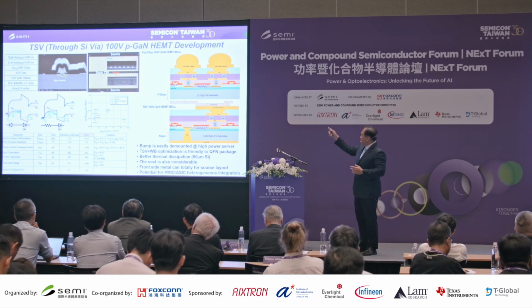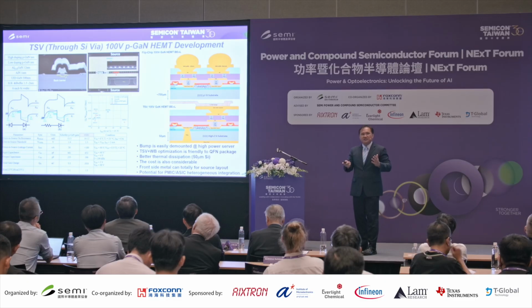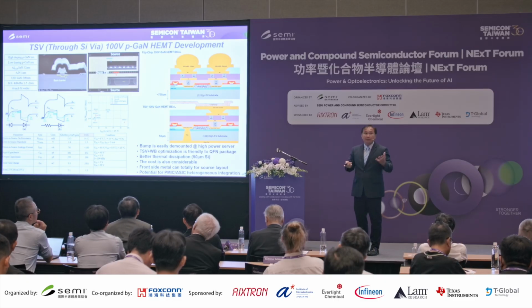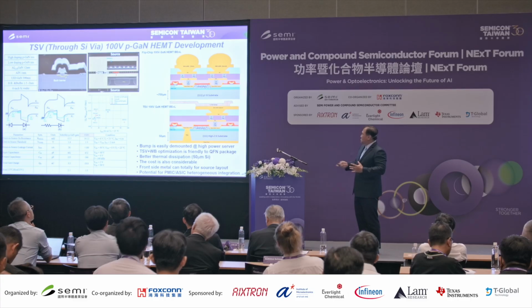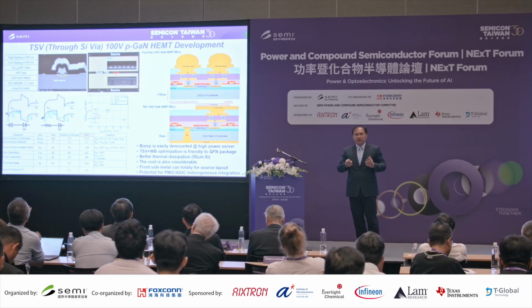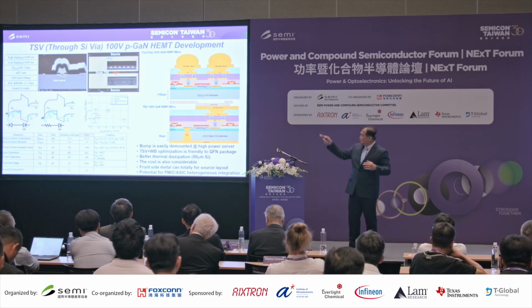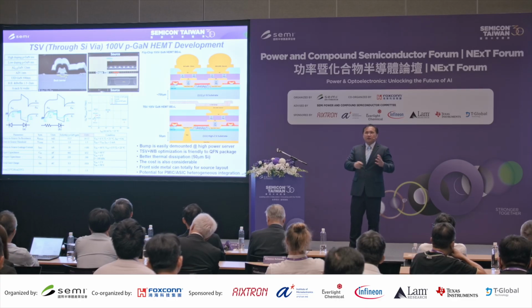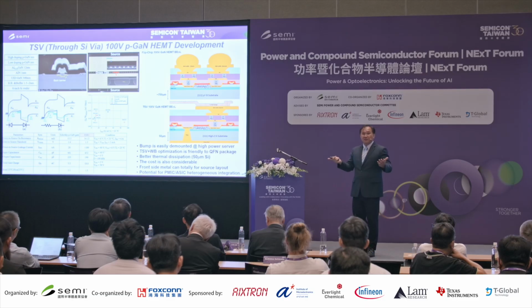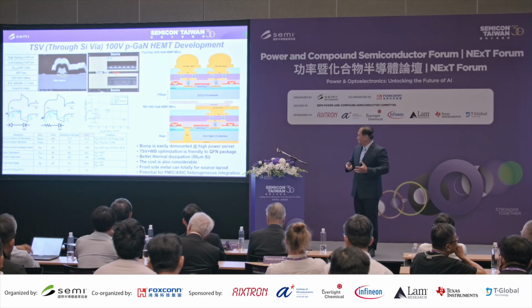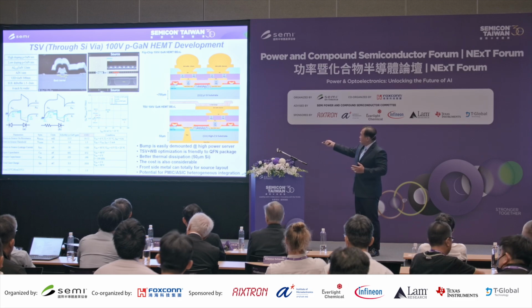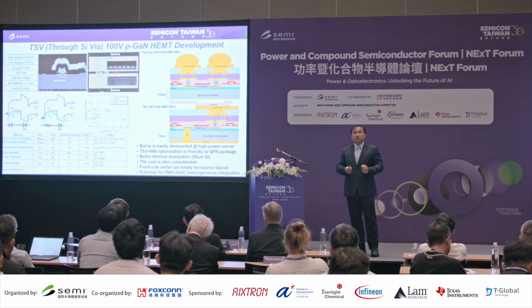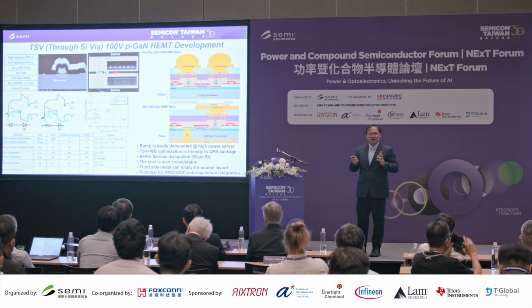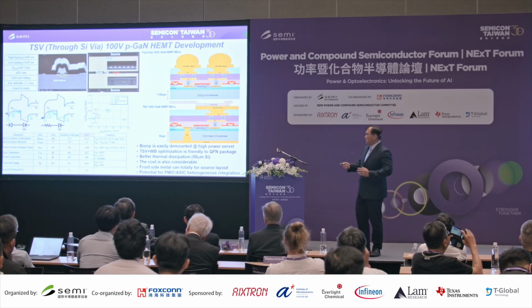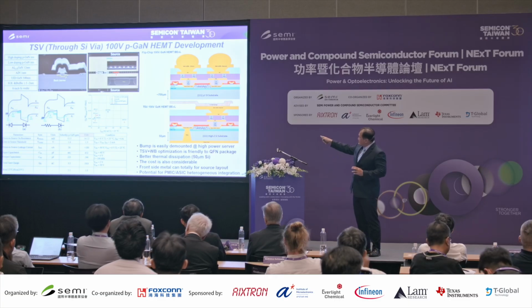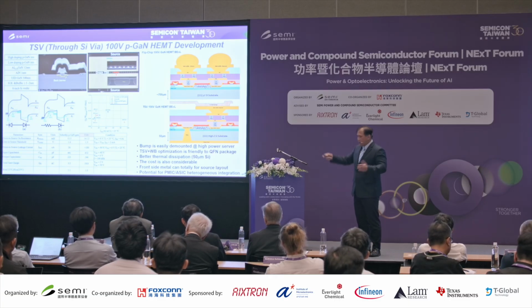So for the system level, the package, you don't want to influence your on-resistance from the package, so the best solution is still the copper pillar or copper bump. But for the bump, it's very easy to demount in the high power stress. So you may notice the yield for the secondary side is only 50%. Sometimes you suffer the bump demount issue. But for our proposed device, we use the TSV for gallium nitride power device, because the backside via is a very regular process in compound foundry, and we just move the drain pad through the TSV to the backside metal,